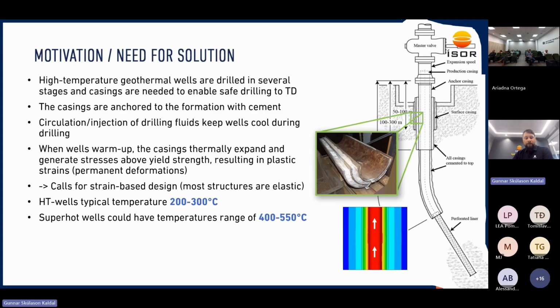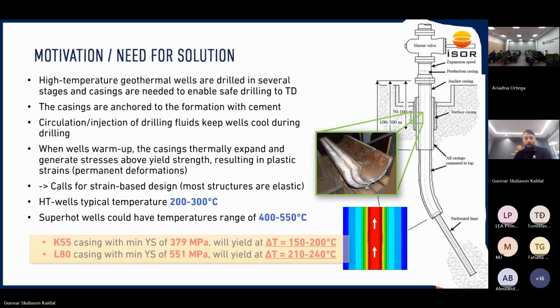The typical temperatures we're dealing with in high temperature wells are about 200 to 300 degrees, all the way up to maybe 350 in some extreme cases. But in the super hot region, we are looking at 400 to 550 degrees even. And if we have the current structure like it is today, then the most common casing materials will go past the yield strength at around 150 to 200 degrees for K55 and 210 to 240 degrees for API L80 materials.